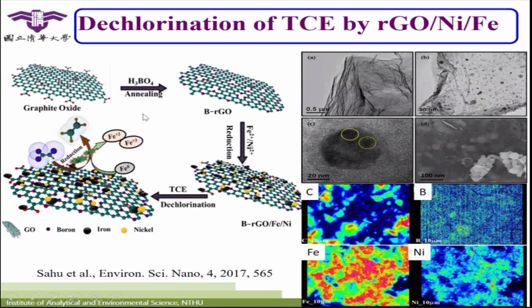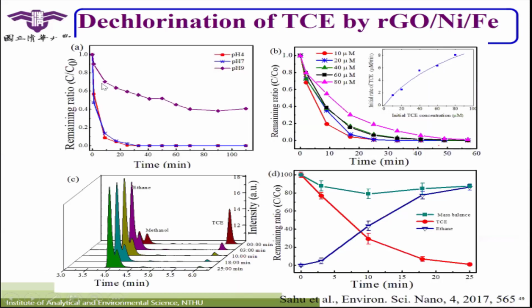We just use boron-doped reduced graphene oxide and put on iron and nickel, and then they will reduce this to zero-valent iron and nickel. So we use this to decompose trichloroethylene, a chlorinated compound. In just around 20 minutes, all the chlorinated compounds can be decomposed, and they will convert into ethane. That will be good.